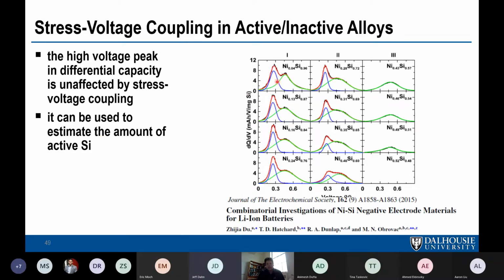Well, if you're eating away at one of these peaks in the voltage curve because of stress potential coupling, how do you know how much silicon is active in the material? And the way to determine that is by fitting the differential capacity curve as best you can, like with Gaussian functions, and realizing that this upper potential delithiation peak is never affected. So if you calculate from this initial differential capacity what the fraction of the capacity in the upper potential peak is, then you can track how much silicon is actually active as you add nickel.